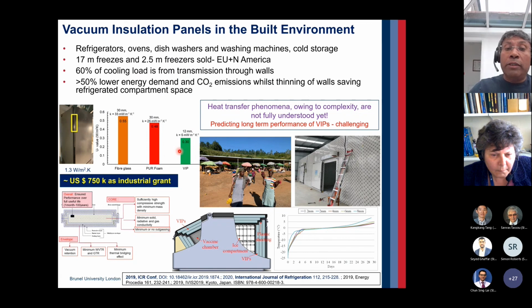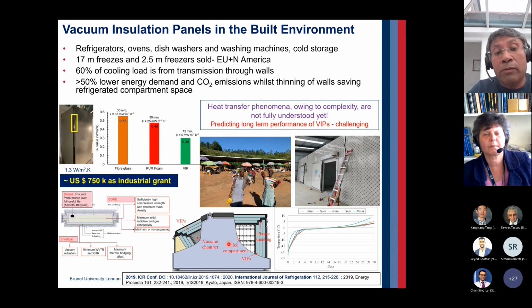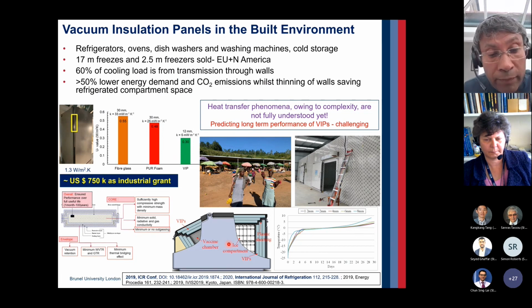We've also shown their use in cold storage in Kenya. And in the past we developed a vaccine storage device for the Bill and Melinda Gates Foundation using VIPs. The target here was to maintain the vaccine at temperatures of 2 to 8 degrees centigrade for about 40 days, when used in places like Zambia or deeper in Africa, where power is not easily available. There are plenty of publications in the area. Some of them are listed here, and you're welcome to read them.